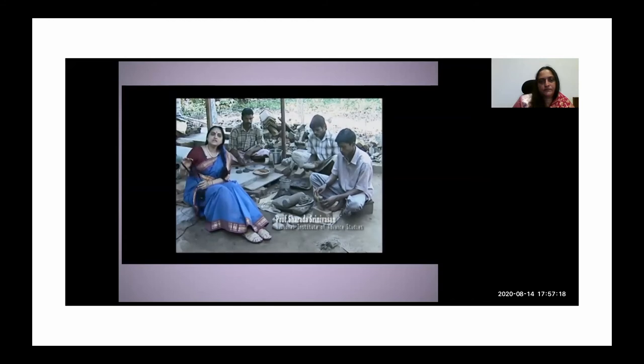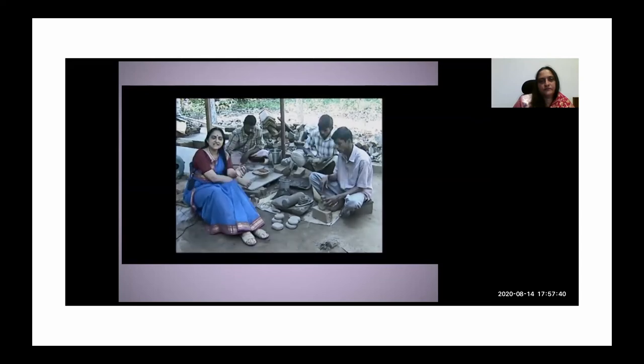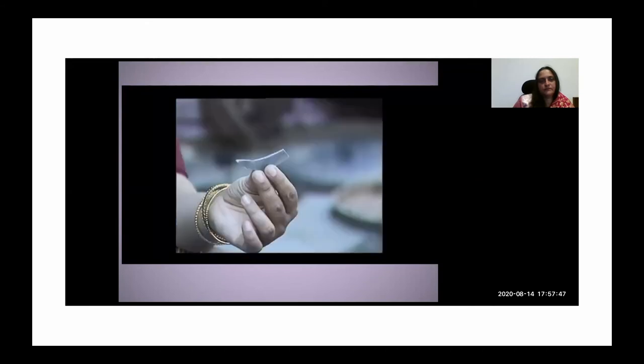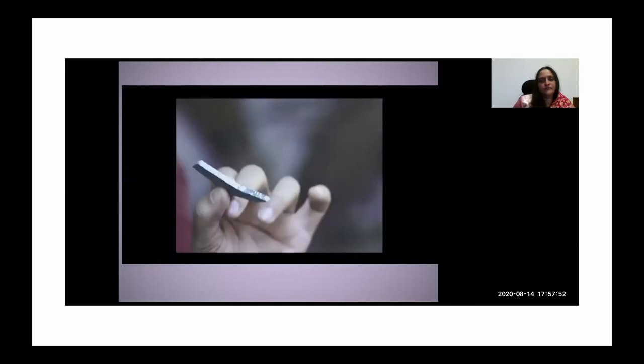Aranmula, which is in Kerala, a little village where traditional metal mirrors have been made for at least the past 200 years, as far as we know. And these are made of a higher tin content bronze with about 33% tin, which I studied and analyzed. This is what I call a delta bronze alloy. It has 33% tin in bronze. And this I found out by microstructural and SEM analysis. And this alloy is chosen because, as you can see, it's a very silvery white color.